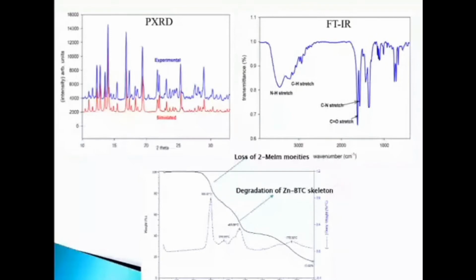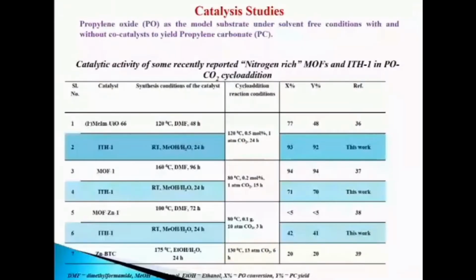From the FTIR spectrum, the broad band at 3440 cm inverse corresponds to NH stretch, which indicates the coordination of mono-substituted imidazole unit, and the absence of peak at 1720 cm inverse confirms the complete deprotonation of BTC linkers. And from the TGA curve, it is understood that our MOF ITH1 is thermally stable, which is due to hydrogen bond. And let us move on to catalysis study.